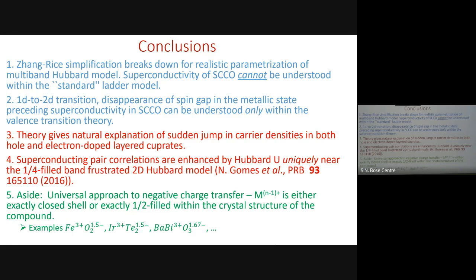So the one exception that I have is nickelate, on which we work, but the bismuth oxide, I would say that this, I said bismuth 3+, there is no bismuth 5+ in it. d8 is also t2g completely filled and eg half filled, right? So that's why I said, no, eg is half filled. The rare earth nickelate. So Dr. Dasgupta has a paper on that.